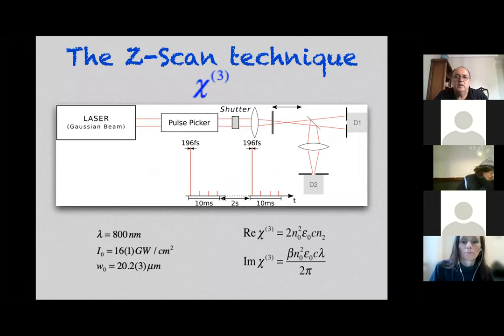So because of that, what we did, we put a shutter here also, and this shutter will cut all these small pulses, which will reach the sample during 2 seconds. And with this, we are absolutely sure that we don't have any thermal effect. How are we sure? We measure the thermal effect. We measure with and without this 2 second shutter here, which cuts completely the laser shining in the sample. And we see that this is independent of the other parameters that we have. So the heating of the sample is really a problem, but we can arrange this from the experimental point of view.